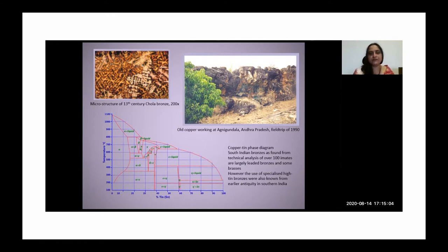Well, that is one type of alloy. And I'll also discuss the mirrors, the mirrors of delta bronze, as I call it, which have a composition approximating about 33% tin in bronze, again, unleaded. And there you see, as you go up to a temperature of about 500 or 600 degrees, you see that Greek letter again, delta. So again, that delta under rather rapid cooling conditions forms even at room temperature. And that's what gives the silvery color, reflective quality of the mirror that you saw in the first picture, which was actually almost as good as a modern mirror. And I should take you to the steps of how those were made.